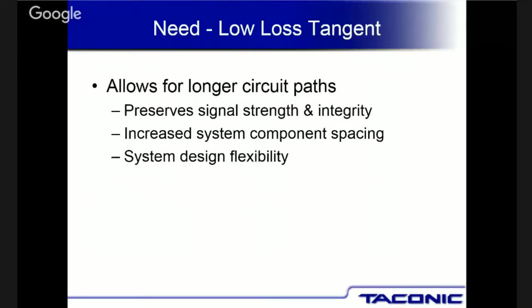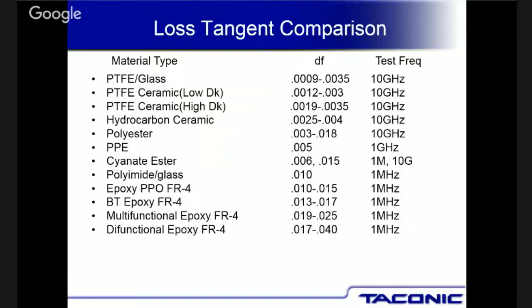And so the lower the loss, the more of the signal gets propagated. The higher the loss, the less signal is propagated. And so there's all different types of dielectric dissipation factors in the material. And like I said, it preserves the signal strength and the integrity. And so again, I'll switch over to this and look at these same type of materials. And so when you look at this, and these are ranges, I guess, the PTFE glass material is the best.